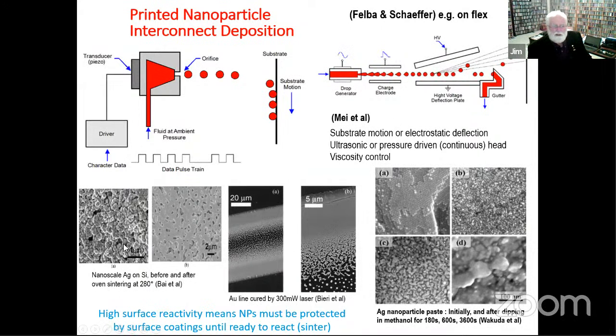Here's some examples of sintering. So this is a paste of nanoparticles deposited or printed or whatever. And this is after sintering in an oven, or you can do it by laser heating. The one that's interesting to me is this sequence of events here. This is nanoparticles as printed, and then at some time later, 3 minutes, 10 minutes, and an hour, the nanoparticles have coalesced.